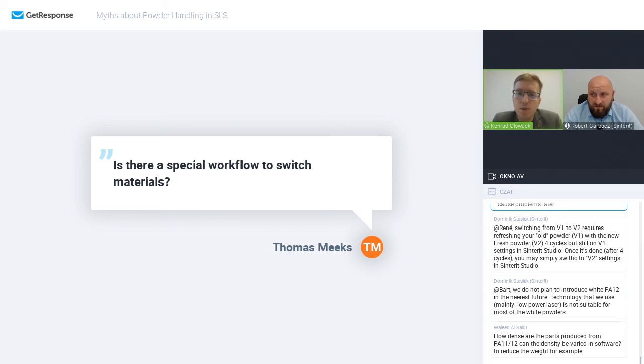Going from rubber back to PA12, because when you work with rubber, the melting point is below the temperatures we hit with PA12 and PA11. So if you don't clean it properly, it will burn within the printer. That's why it's a really detailed cleaning, and 20 minutes will do the job for the full switch. In our system there is a special step for material switch, so you have the whole instruction on how to do that on the machine.